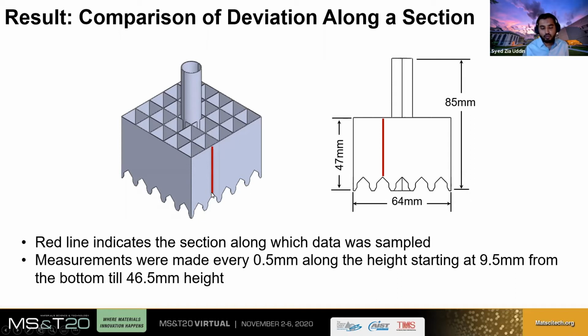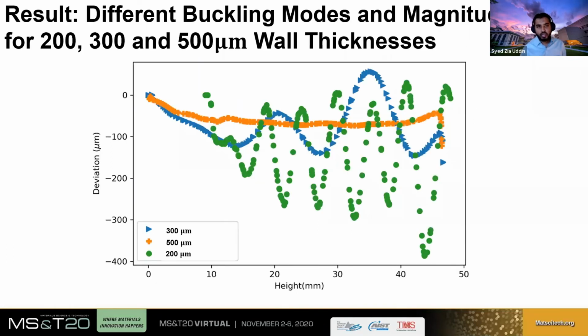So we're basically taking the worst case scenario for every deformation case, I mean the worst possible deformation scenario of a given wall thickness part. We're choosing one of the cells and taking the deviation measurements along the height of that part and plotting them against the height. As shown in this graph, we're seeing our three different wall thickness parts: 300, 500, and 200 micron. They were fabricated using the laser powder bed fusion process and then scanned, and the scanned STL is compared with the CAD model, and these are the deviation data that we get.